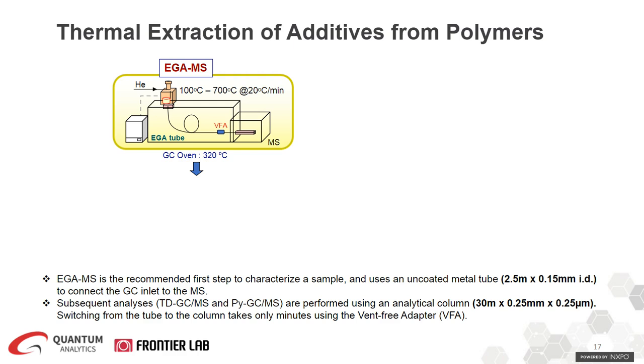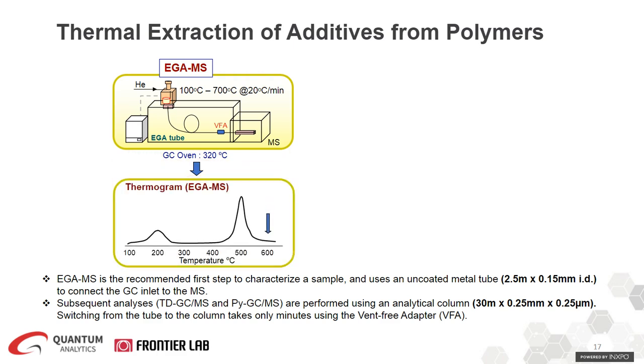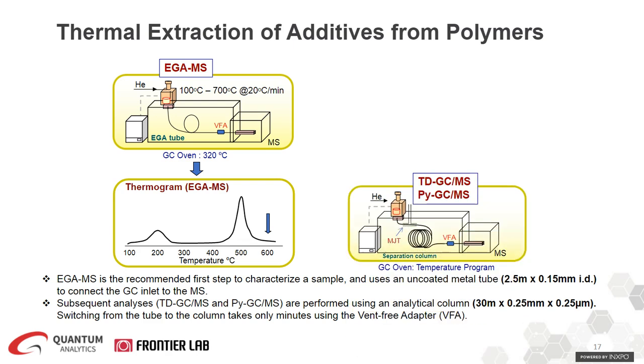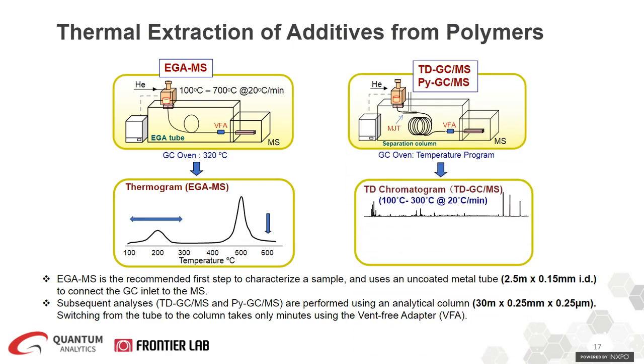Now we discussed thermal extraction. So first step is to run your evolved gas analysis. In this case, it was done from 100 to 700 degrees at 20 degrees per minute. Notice the EGA tube and keeping the GC oven isothermal. Then you'll obtain an EGA thermogram. The x-axis is your temperature and the retention time, and the y-axis is your intensity and concentration. So now to analyze the first peak or the hump from your EGA thermogram, you have to switch the EGA